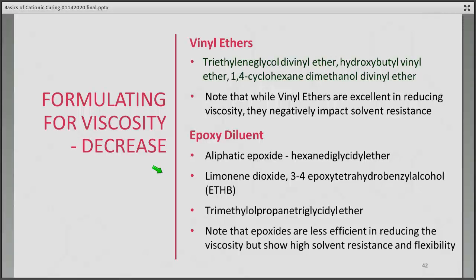Epoxy diluents can be used, like an aliphatic epoxide. Limonene dioxide is commonly used, or ETHB is another one. But something to remember if you're using epoxies to dilute is that they're less efficient in reducing your viscosity. However, a real upside to using them is that they have high solvent resistance and add some flexibility to your system.